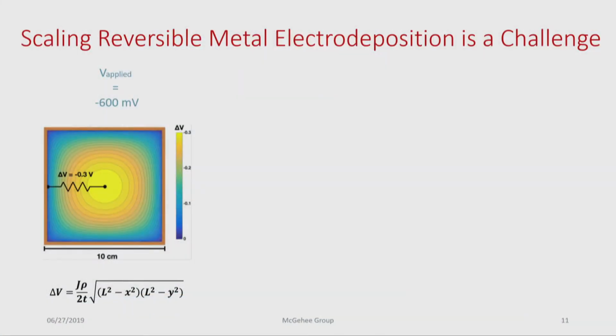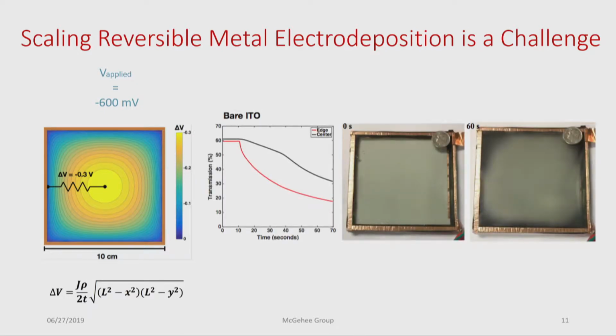The reason is that when you apply a potential to the edge of a TCO, you have current rolling through this material. And if you think about Ohm's law, if you have current running through a resistive material, you're going to experience a type of voltage drop. So we have a voltage drop here in this TCO from the edge to the center. If you combine this voltage drop with the poor metal nucleation properties of ITO, it will cause metal to preferentially plate on the edges rather than on the center. So when we try to scale this up to 100 centimeters squared, you can see that we aren't able to achieve uniform tinting. So this is completely not going to work for any type of real-world fenestration applications.